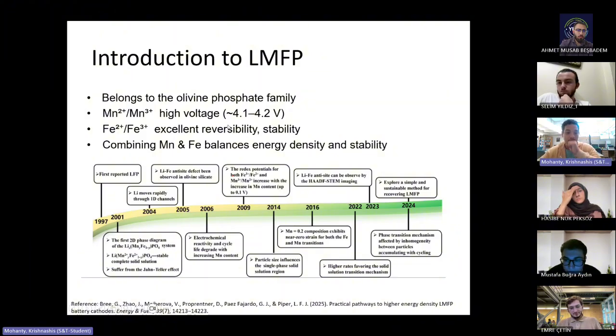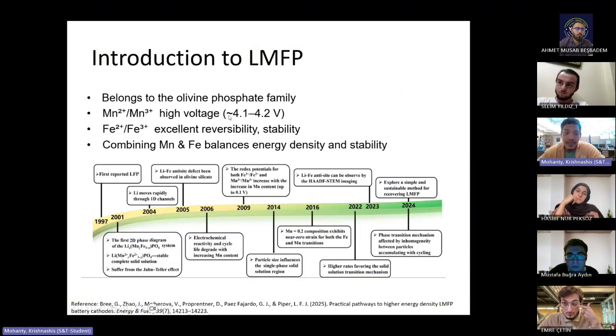So, okay, now what is LMFP? LFP, as we would know, is lithium iron phosphate, and LMFP is just manganese doped into the very structure. LMFP belongs to the olivine phosphate family. The olivine phosphate family is derived from the word olivine, which is a mineral, and it has a structure similar to this. And because of this structure, it is very stable. And this structure is actually useful in all electrochemistry as well. I'll go more into that when we reach that slide. But yeah, olivine is just because of its structure.